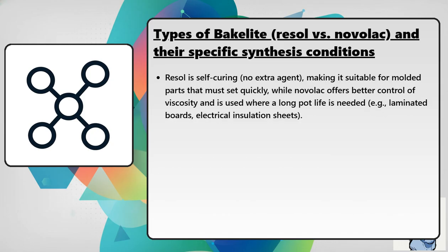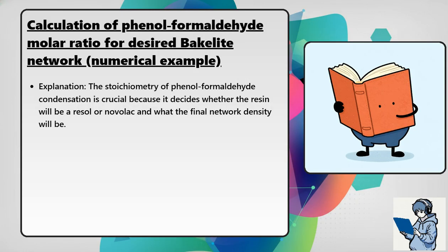Resol is self-curing, no extra agent, making it suitable for molded parts that must set quickly, while Novolac offers better control of viscosity and is used where a long pot life is needed, for example laminated boards, electrical insulation sheets. Explanation: the stoichiometry of phenol formaldehyde condensation is crucial because it decides whether the resin will be a Resol or Novolac and what the final network density will be.